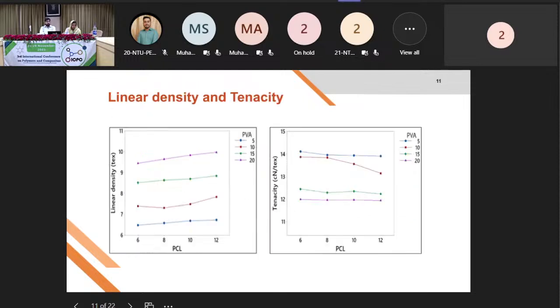With increasing polyvinyl alcohol concentrations, the material's linear density increases, which explains that the material becomes more viscous, and hence because of the higher viscosity, a thicker fiber material is achieved.